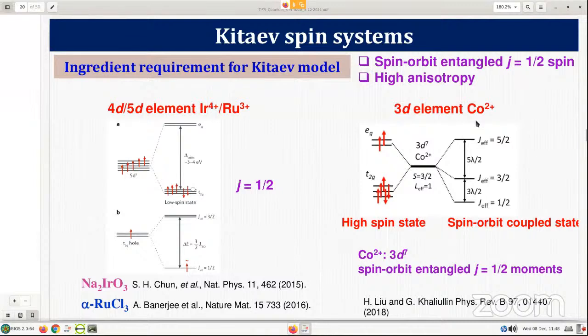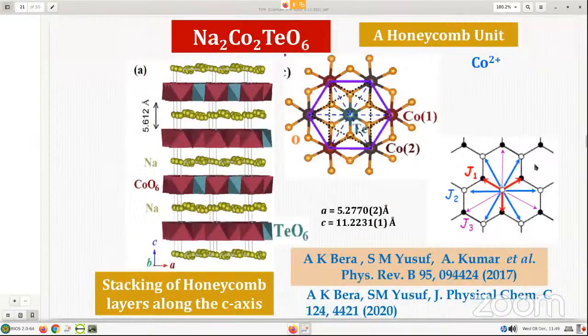But the question is about 3d systems, for example cobalt 2+. In 2018, in this paper, Khaliullin et al. showed that indeed a 3d cobalt system, cobalt 2+, under spin-orbit interaction, can also have effective J equal to half. After this literature report, we thought, let us venture into this kind of system, cobalt 2+ in this Na2Co2TeO6 system, where cobalt forms the honeycomb lattice, because this is another ingredient. So honeycomb lattice with cobalt 2+ is a potential system for a Kitaev kind of phase.